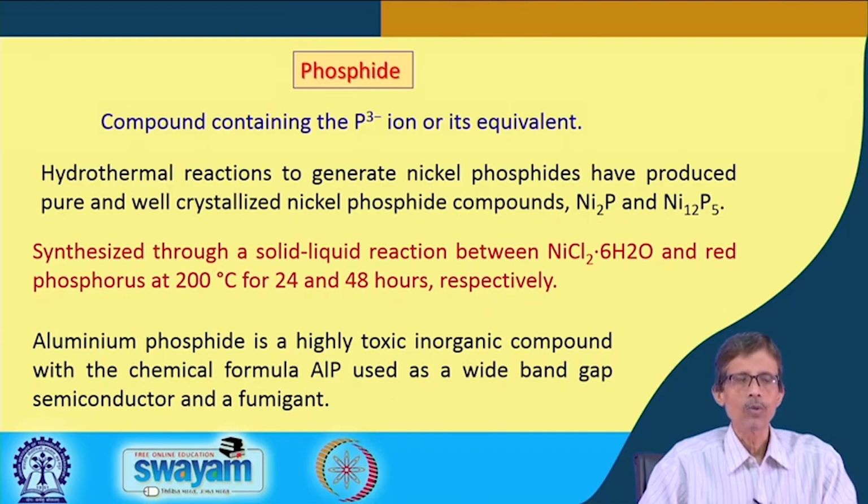That is a solid-liquid reaction under hydrothermal condition at an elevated temperature of 200 degrees centigrade, maintained for a time frame of 24 to 48 hours. So, this will give you not only the formation of your nickel phosphide, but also in its crystallized form. Similarly, aluminum phosphide, where you do not have any problem regarding the formula, you simply write